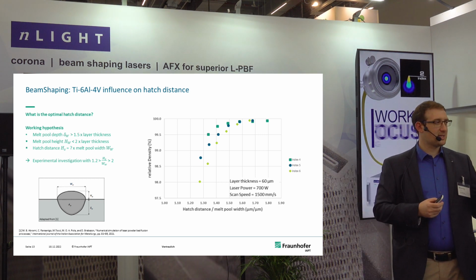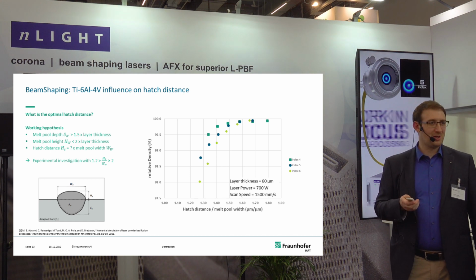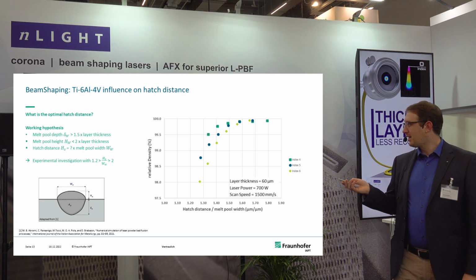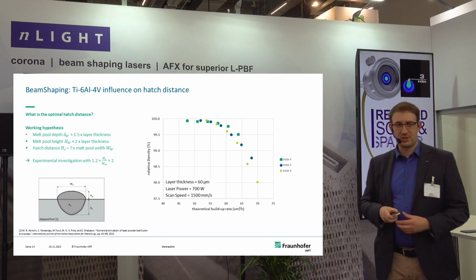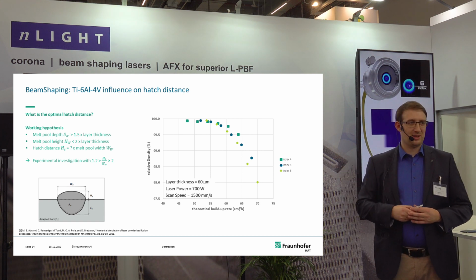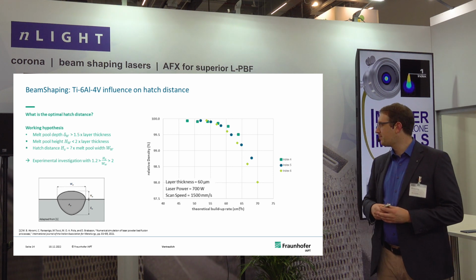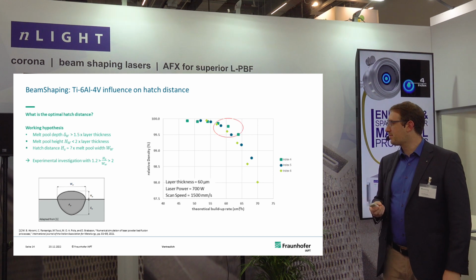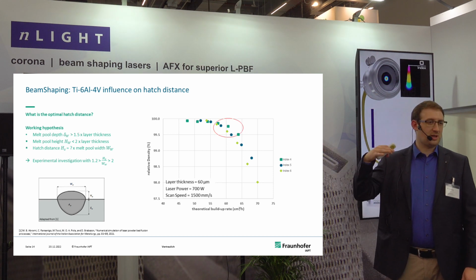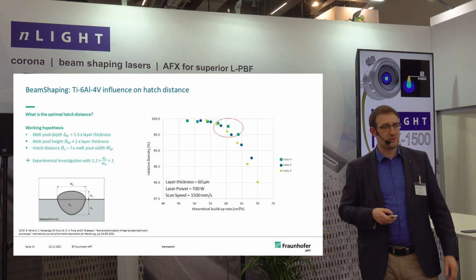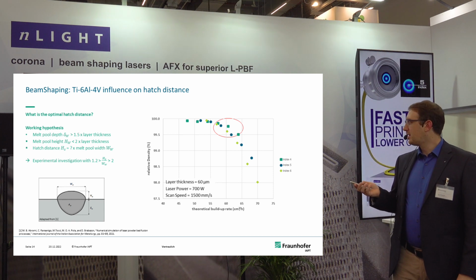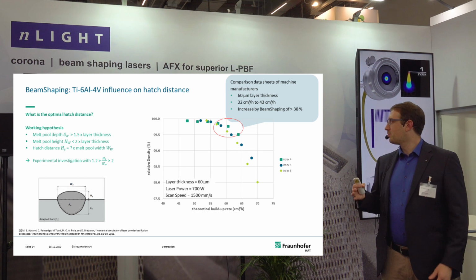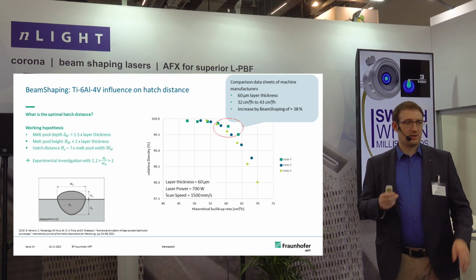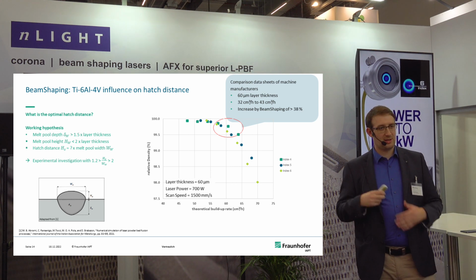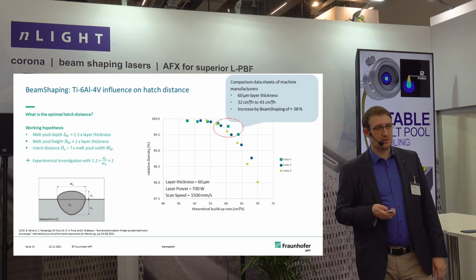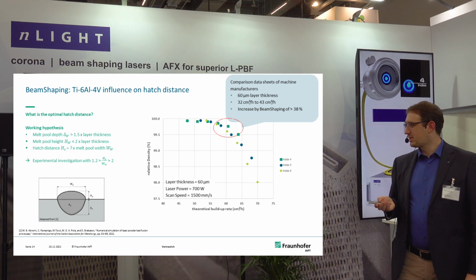The physics behind this we are still investigating, so there we'll probably follow up with a research paper. But what does this mean in terms of productivity? Same data, just with the build-up rate on the x-axis now, where we can see, in the range of interest with high relative density, 99.5% and above, we're between 55 and 60 cubic centimeters per hour. If we compare this with data sheets from OEMs, same layer thickness, similar laser power, we notice that we can increase productivity by at least 38% only by changing the laser system, which is quite nice.